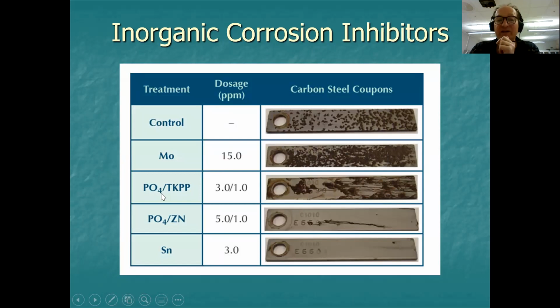If you then put in phosphate, I'm not sure what TKPP is. That sounds like a product name. I'm not quite sure what that is. But the phosphate is the important thing here, in the range of 3 to 1 parts per million. Then you can start to see some effect. If you then put in another type of phosphate formulation, this contains zinc, then you can see a huge difference here. There's very little corrosion compared to these other samples. And if you use tin, it's a tin-based corrosion inhibitor, then the only corrosion I can see is that little spot there. There's almost no corrosion on the rest of the surface.